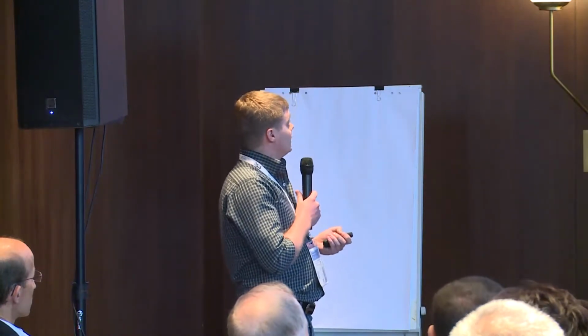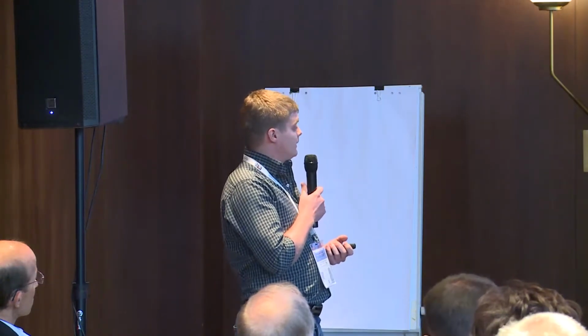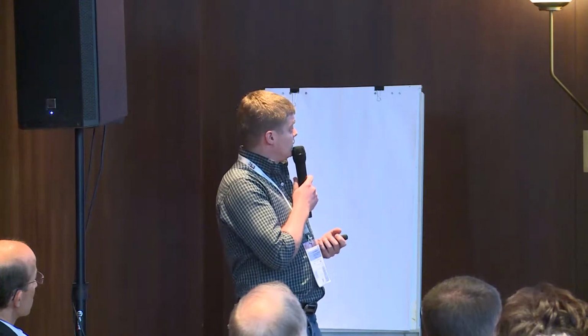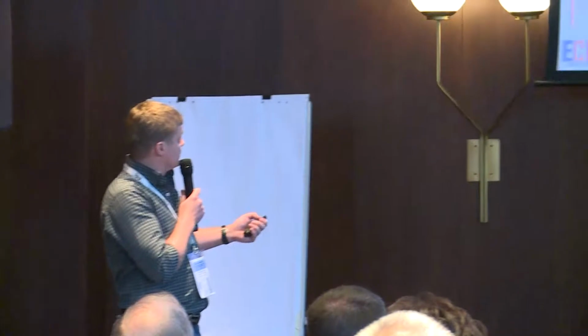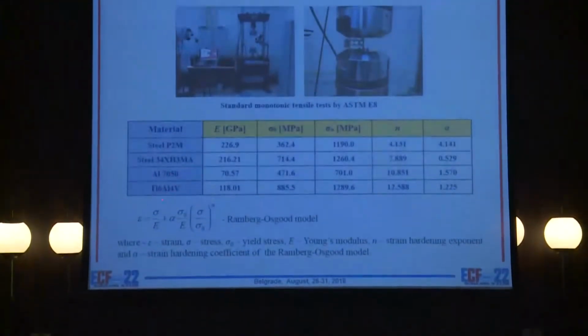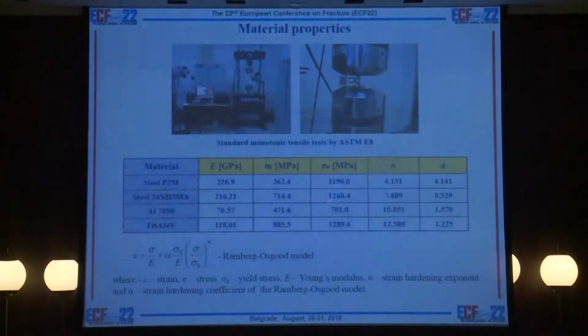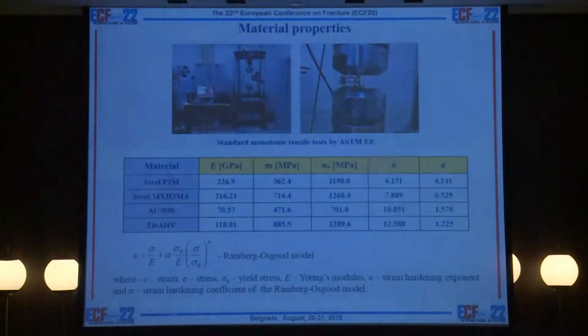In this study, in order to characterize mixed mode conditions, we used the plastic mode mixity parameter in the following form. As I said, one of the main aims of this study is evaluation of the effects of elastic plastic material properties. So we considered four types of materials: two types of construction steels, an aluminum alloy and a titanium alloy. The main mechanical properties for each material were obtained by standard tensile tests, and stress strain curves for each material were described by the well-known Ramberg-Osgood equation. These mechanical properties are the basis of our finite element modeling.